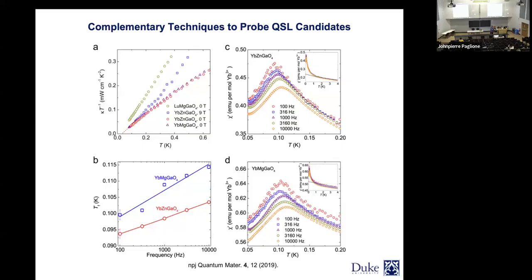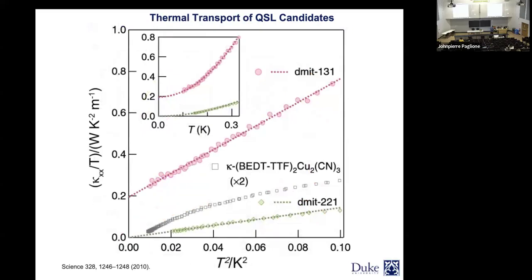And then here's an example of thermal conductivity for a quantum spin liquid candidate, which is what I'm talking about. You can see here, this is for a magnetic compound, and this is for a non-magnetic compound. It starts to give a finite value as we go to the lowest temperature, and here is another one that plateaus. So this is indicating that even at zero temperature, you have spinons or magnons that are contributing to the thermal conductivity.